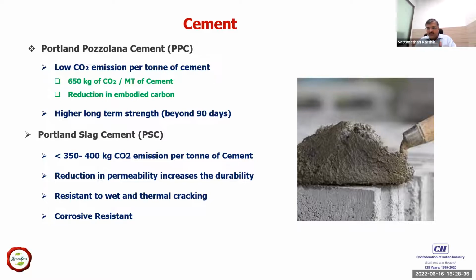Another aspect is, because we are using cementitious material in this, the strength gain over a period of time is in fact much better than an ordinary Portland cement. We have some cement experts in the next panel, and you can have more information from them. But the point I am trying to make is, in case of OPC, you may gain some one-day strength, whereas in case of PPC, the strength gain is much more over a period of time. So we always recommend going for a blended cement compared to an ordinary Portland cement.